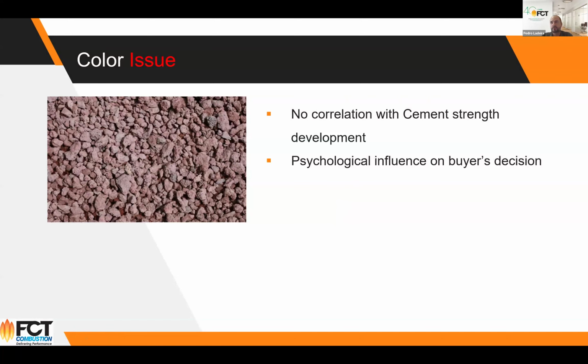Some buyers, I would say most of them, are really concerned about presenting to the market a certain palette of color and try to avoid the red. So what is behind that is how to deal with this. If most of the clay after burning becomes hematite, it will become reddish. If you can get it to a high temperature and keep it in the magnetite form, then it might be possible to have a different color, tending to gray or black.